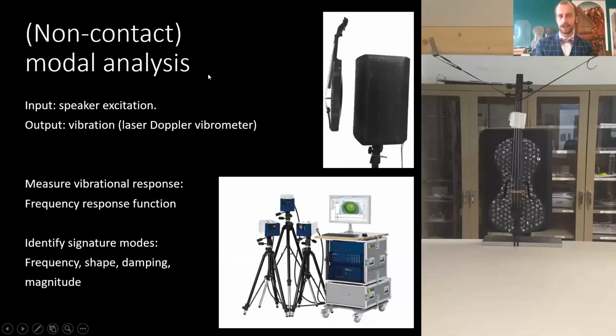And so first I did a modal analysis. We did it in a non-contact way. This method has been used by Romain previously with a speaker to excite the instrument, and then the violin is before it, and you measure the output, the vibration of the instrument, with the laser Doppler vibrometer. I will not go into detail too much, but the idea is that you let the instrument vibrate and you measure the response. So you get the frequency response function of the instrument, and that allows you, together with a certain software, which was Polymax, to then identify the signature modes of the instrument. These modes have been talked about in other presentations, so I will not go into detail too much.